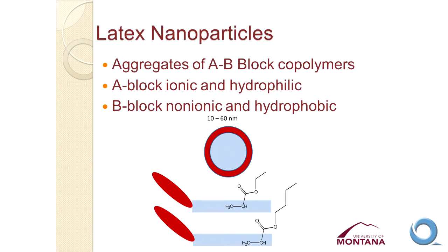So what we're working on now is the use of latex nanoparticles as pseudostationary phases. We form these latex nanoparticles, and they are actually aggregates of AB block copolymers, where the aggregate looks something like this. This is just a cartoon, of course. In the core we have a hydrophobic block of a copolymer, and around the shell, we have a hydrophilic ionic block of the copolymer. We've been synthesizing these, it says 10 to 60 nanometers, but I will show you some results today where we've synthesized some that are as high as 100 or 120 nanometers.